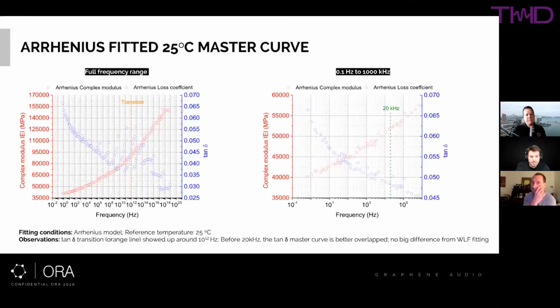We use a method called TTS, which is time temperature superposition. Basically, we measure the Young's modulus at different temperatures and then use a mapping function to determine how those temperatures relate to different frequencies. We can then map from the temperature domain to the frequency domain and determine our modulus versus frequency up to very high frequencies.